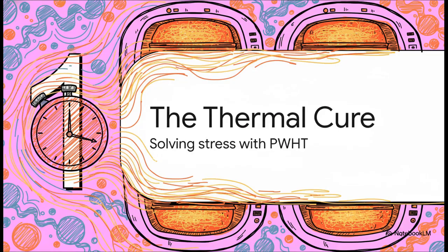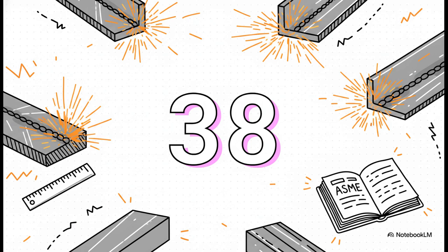The thermal cure, solving the stress problem with Post-Weld Heat Treatment, or PWHT. So, how do we disarm this ticking time bomb? When is this giant thermal massage actually required? Well, in heavy engineering, there are really strict rules governed by international standards, like the ASME code. For standard carbon steel, the absolute golden number you need to remember is 38. Once the thickness of that steel plate hits 38 millimeters, the risk of trapped stress gets so high that post-weld heat treatment becomes absolutely mandatory. You simply cannot skip it.